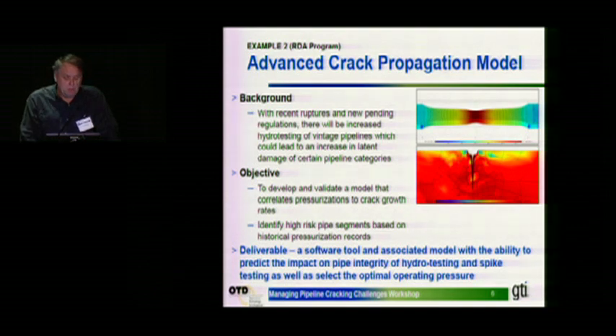The deliverable here will be a software tool and associated models with the ability to predict the impact on the pipe integrity of hydro testing and spike testing, as well as select the optimal operating pressure. So this is a very interesting project because we're actually modeling dynamic crack propagation here, and there's quite a lot of sophistication that goes into that to address things like elastic plastic analysis with strain hardening and notch tip blunting, crack arrest, not just crack propagation. So it'll be a very nice tool when it's completed.